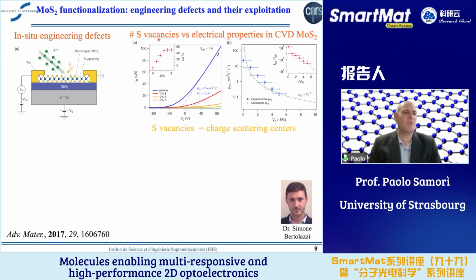Of course, the generation of more and more defects is also accompanied by a lowering of the electrical characteristics of the CVD MoS2. And you can see here in the center how the mobility is decreasing. Well, actually, we just see here how the current is decreasing through the junction, or on the right, how the mobility is decreasing with the increase of the number of defects, or defectiveness, of our molybdenum disulfide.